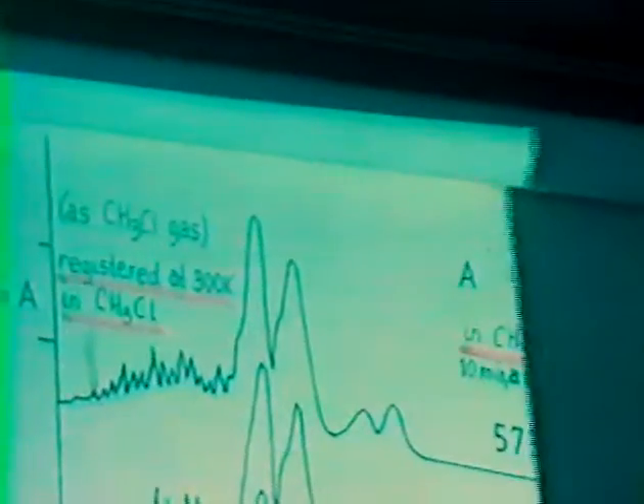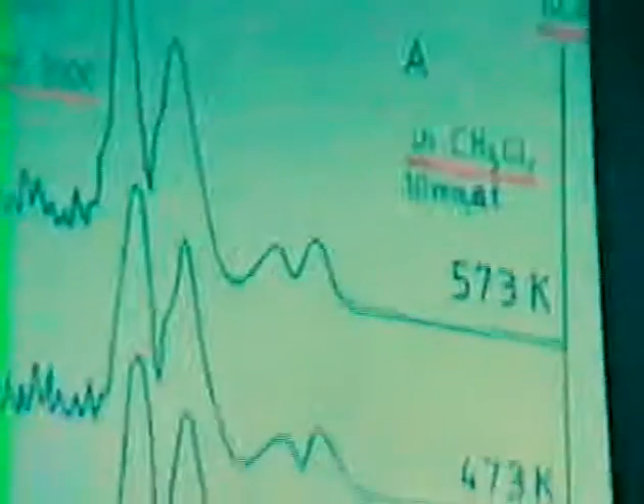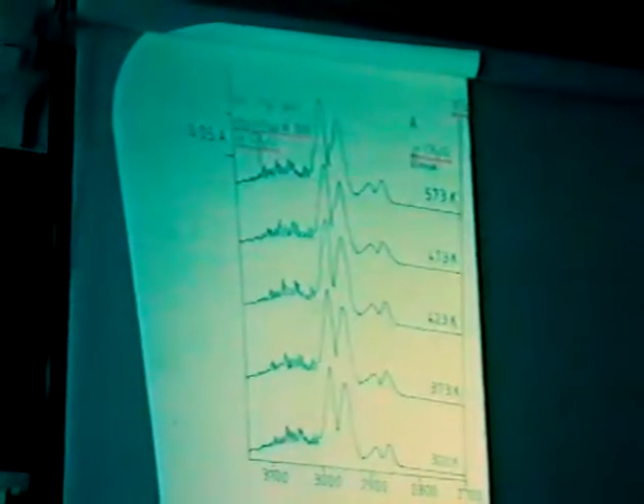Another type of experiment, when our sample was kept in methyl chloride at the temperature indicated here for 10 minutes, and after that the sample was cooled down to room temperature and the spectra were registered. Naturally, the spectrum of gas phase methyl chloride masked the whole spectra of surface species. That's why we have evacuated the gas phase at room temperature and we obtained the spectra at the right part of this figure. Again, the band at 2920 can be detected up to 473 Kelvin as a sign for the presence of surface methyl group.